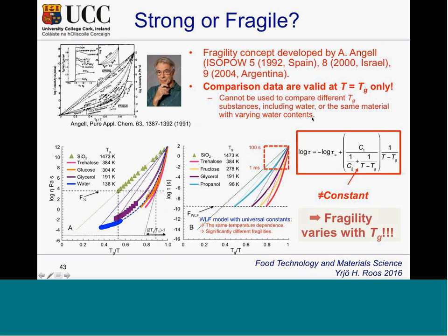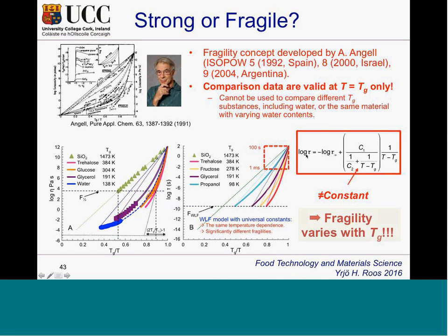You may see some papers by Professor Angell, and he has made this fancy diagram with a lot of materials, saying that if we have silica glass, it's very Arrhenius. Plot the log of relaxation time against Tg over T, and it's a straight line, while some other materials are very curved. So you could measure the curves here and say that they have a different D value. That comes from the Tammann-Vogel-Fulcher relationship, which I will show soon, but here is a material with a relationship converted from the WLF equation.